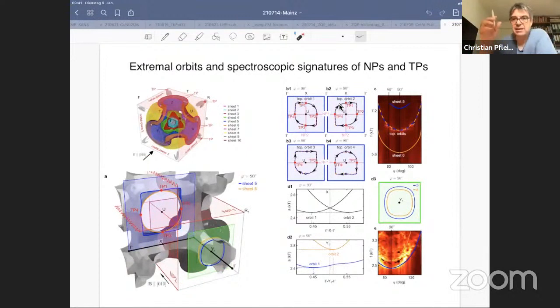And again, there's no magnetic breakdown, right? You have to cut across onto the different segments, so to say. And when you calculate this, you find that there is one frequency, even though you have 4 orbits contributing, right? And it shows a certain dispersion that's also in agreement with the experiment. Whereas if you would have no nodal planes, you would expect frequencies up here and down there. So this is not observed.